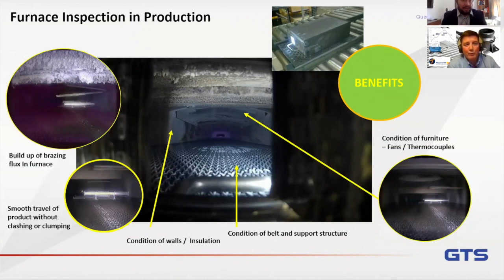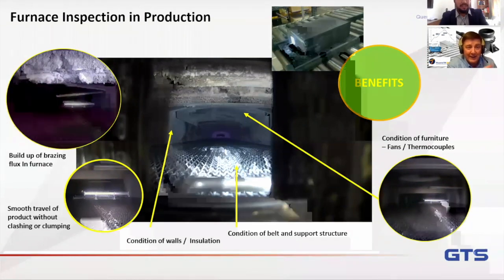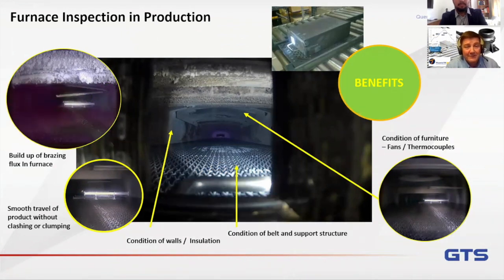I agree. So I think you have really nice pictures here. For example, flux buildup. That looks horrible. Unfortunately, that's a byproduct of the Nocolok process, where you're putting in the flux to clean the surface. At temperature, that's fine because it's in the gaseous state. But when the flux hits the back end of the muffle furnace, when you're getting into the cooling section, those chemicals will condense out of the gaseous phase into the liquid and solid phase, and they'll start to collect on the cooler areas of the furnace, and they create this sort of stalactite type formation, which when I saw it for the first time, I was blown away as to how problematic that could be in practice.